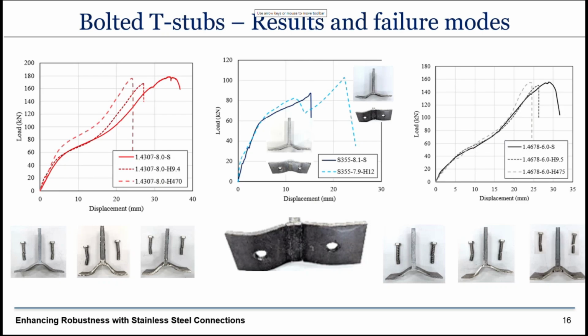So some selected results are shown here. We can see, on the left-hand side, the conventional stainless steel. The solid curve is the static curve, and the dotted curves correspond to a loading speed of 9.4 millimeters per second and 470 millimeters per second. And we can see that we have a significant increase in the yield stress for the higher strain rate, a decrease in ductility, and also a small decrease in the ultimate stress, based on what we observed before about the stainless steel material response at high strain rates.